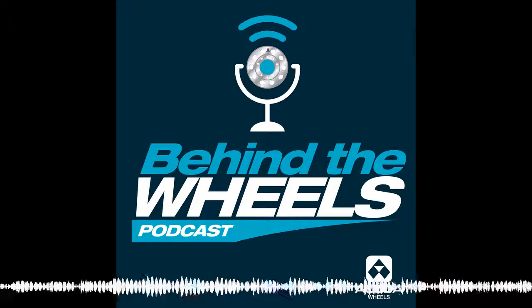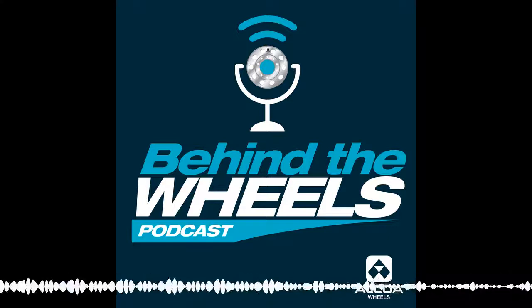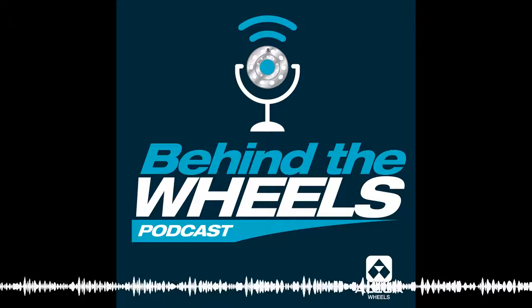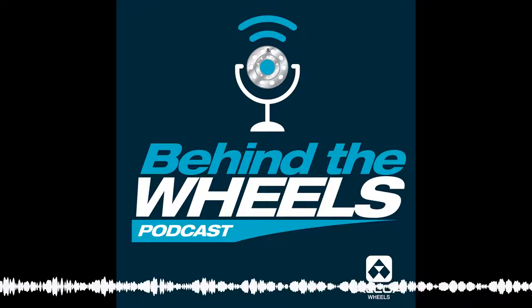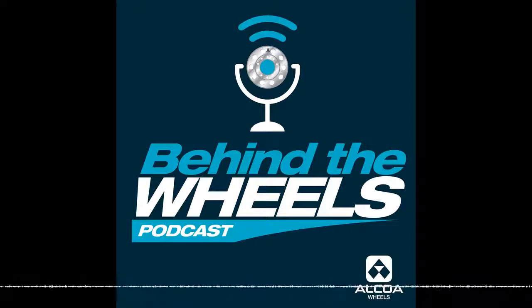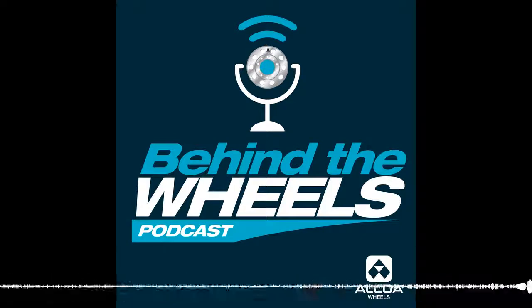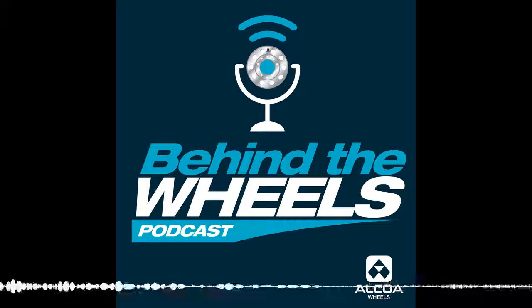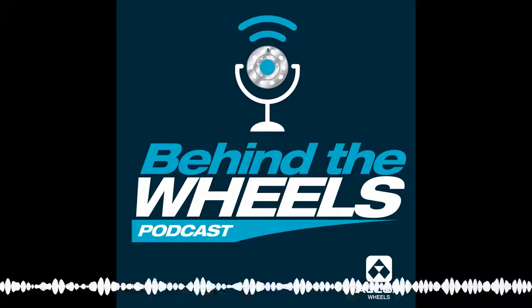So, Doug, you want to take a crack at trying to verbally explain what washout is? Yeah, washout is where you've basically over polished or buffed a certain area, and you get an indentation. One of the main areas of concern is on the hub itself. As you're buffing in the bolt hole area, it's easy to catch and create what I'll call divots, and then you no longer have a flat contact surface. That's a critical situation, both for the mounting surface of the wheel to the hub, and for the wheel nuts, which are supposed to be flat washers on a flat surface. If that isn't the case, you may not be getting the torque that you're expecting. You can have other issues as well. So you've got to watch out for the washout.